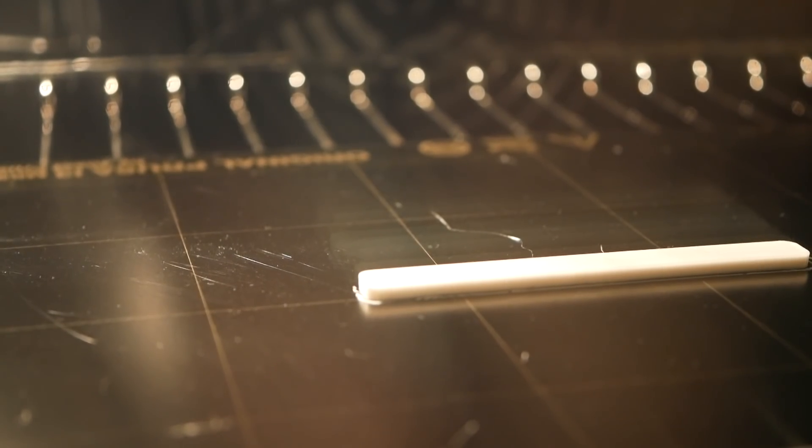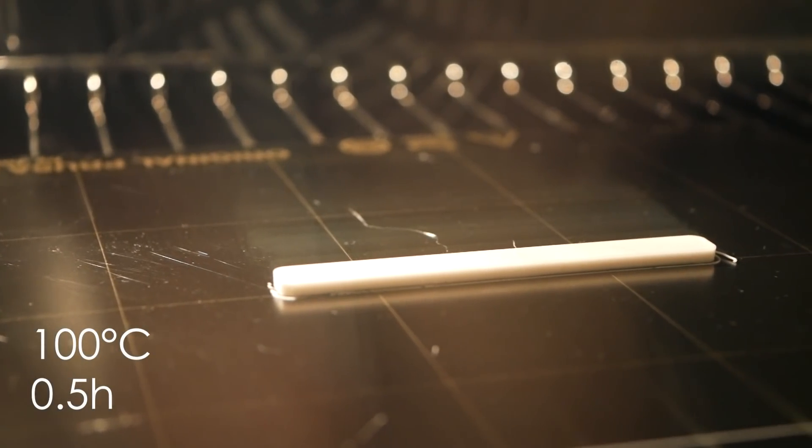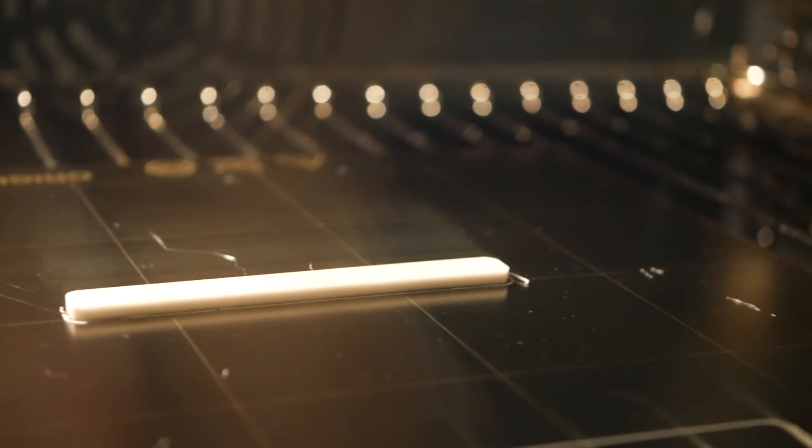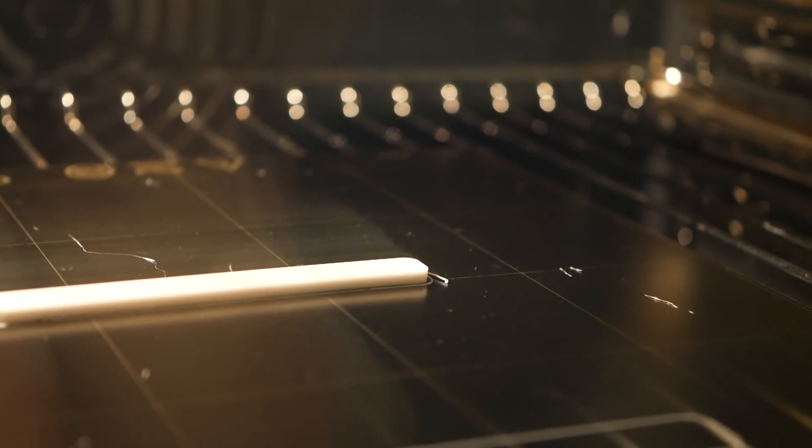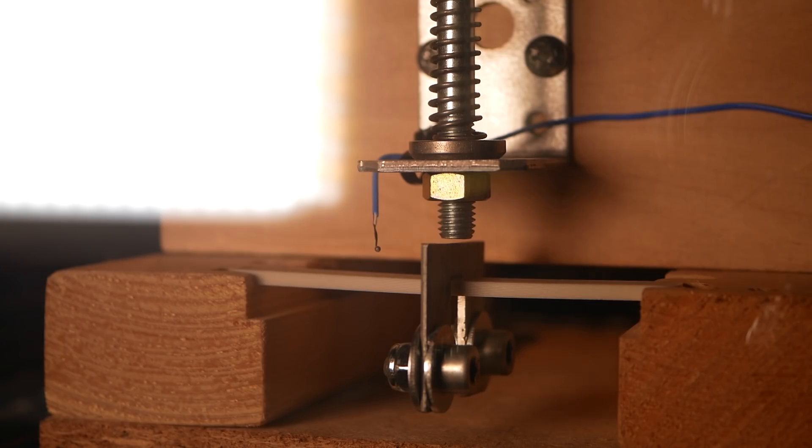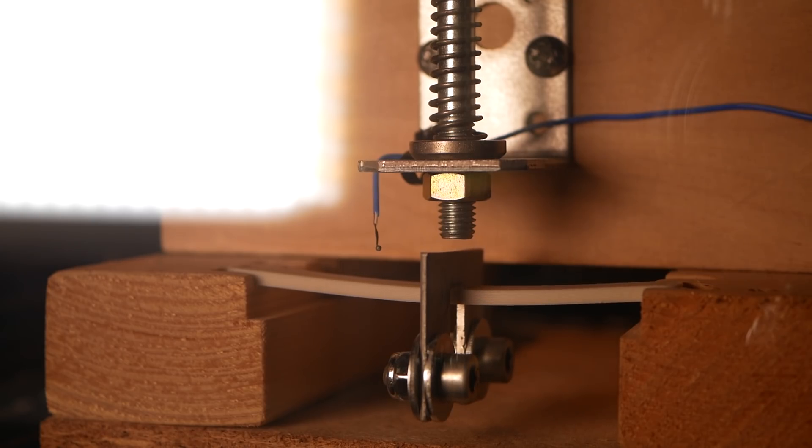I put a couple of test coupons in my oven at 100 degrees celsius for around half an hour and then turned it off and let everything cool down naturally. This let the material crystallize and therefore making it more heat resistant and changed the mechanical properties a bit. These samples were able to bear around 140 degrees celsius before they got unusable. The other test samples only showed minor changes in their mechanical properties which is in my opinion not relevant.